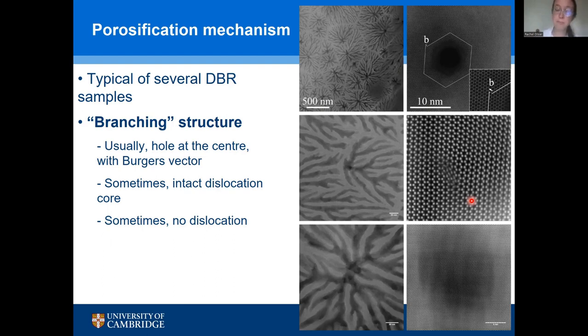it kind of self-forms a pipe. So if we look at the traditional way of making these things, they've dug big holes. And what this way of doing is taking a pre-existing problem in the crystal and letting the etch select for it, and the etch makes its own route then down to the dope layer. And then when it's finished etching that dope layer, it then goes further down that same pipe down to the next dope layer. So it's really interesting.